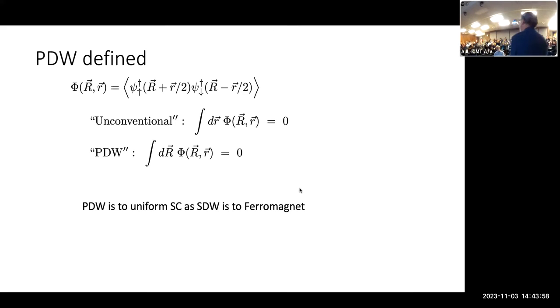There's an analogy that I'm going to make several times here, which is the pair density wave state is to the uniform superconducting state as a spin density wave or antiferromagnetic state is to a ferromagnet. These both are magnetic. They both break time reversal symmetry, but they have very different properties because of their spatial structures.